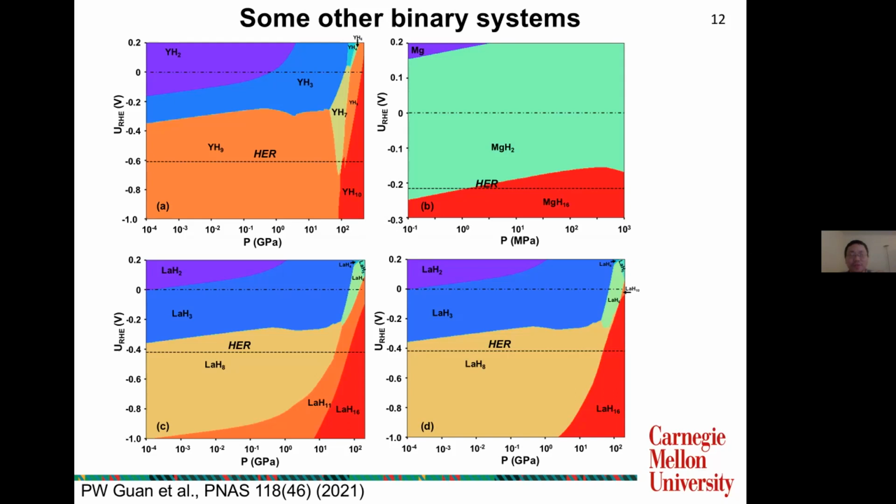So the potential will change the energy of the electron, and thus the relative stability between the system of electron plus hydrogen ion and the hydrides. This is the core idea. But for the metal lattice, I don't think there is a direct effect, because it does not have a charge, so it's neutral.